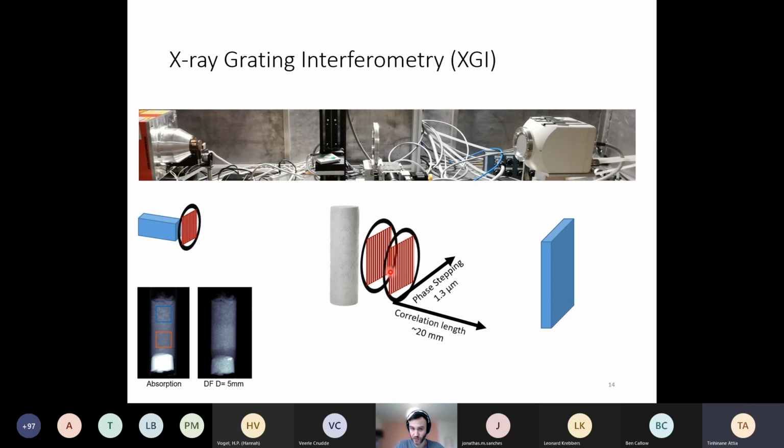So we move the second grating, and thus we are now imaging at a different correlation length, and we see indeed that the visibility reduction changes, this time lighting up the top area. That indicates that the top area loses a lot of visibility at the length that's corresponding with this correlation length, which then corresponds to a size in the nanometer range. So it's really giving you information about what's happening inside your voxels in the nanometer range, which is a really interesting observation.